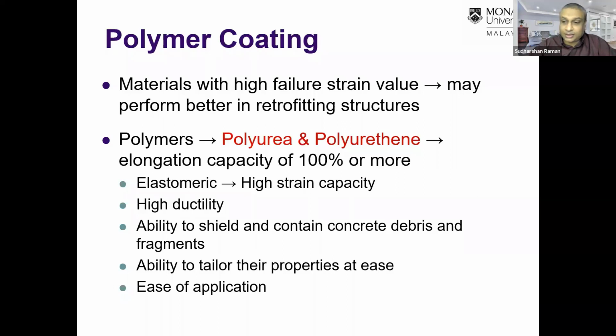Some of the advantages are that they are elastomeric. They have high strain capacity. In our case, we noticed in quasi-static condition, the strain can actually go up to 300%. They are highly ductile. They have the ability to shield and contain concrete debris and fragments during the blast event. They act as a membrane to protect the debris and fragments from propelling. We have the ability to tailor their properties at ease, and they can also be applied easily onto the structure by using spray-on or brush-on techniques.